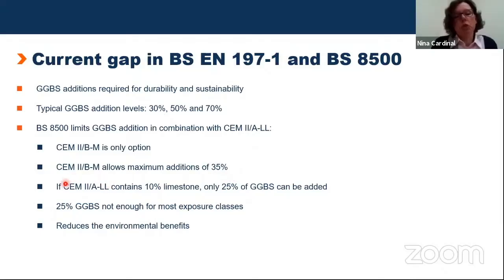Now, if a limestone cement, which is lower in embodied carbon than a CEM1, already contains, for example, 10% of limestone, then only 25% of GGBS can be added. And 25% of GGBS is not enough to meet most exposure classes requirements in BS 8500. And of course, it also reduces environmental benefits because it's actually less GGBS than we would currently use in, for example, the slag cements.